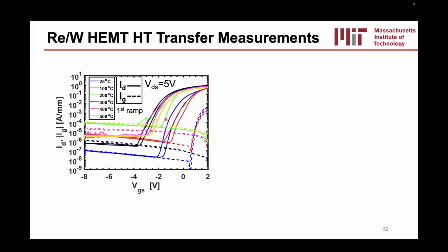If you plot the drain current versus the gate voltage, the blue one here is 25 C, and then it goes to 100 C in red, and then kind of jumps back to 500 C. You can see that this time the threshold voltage is generally to the left, or in a negative direction, which is the opposite of what we saw in nickel gold devices.